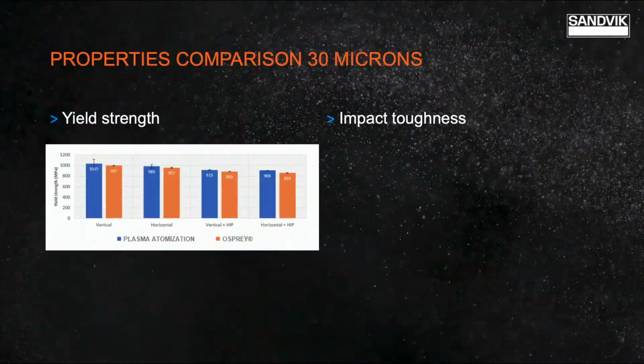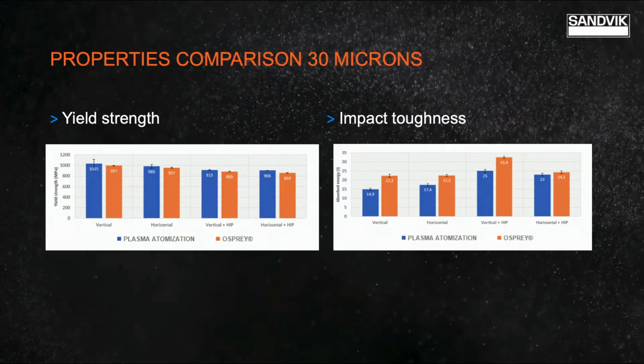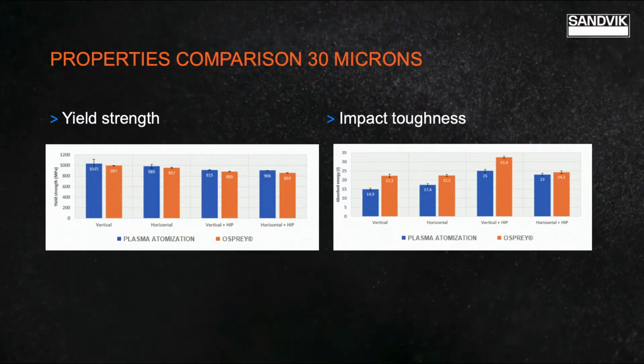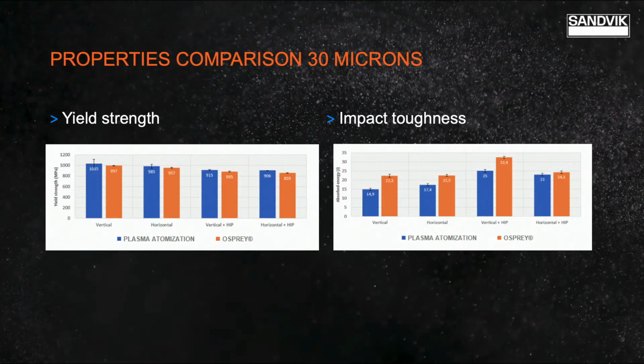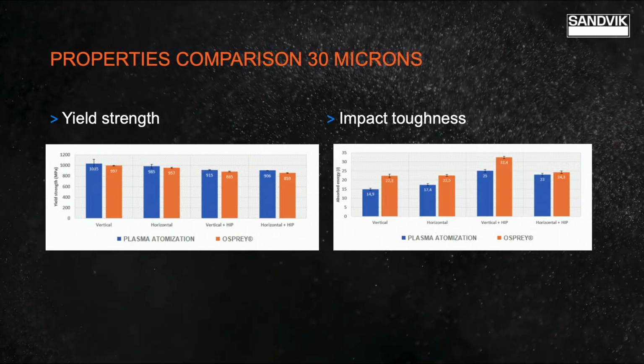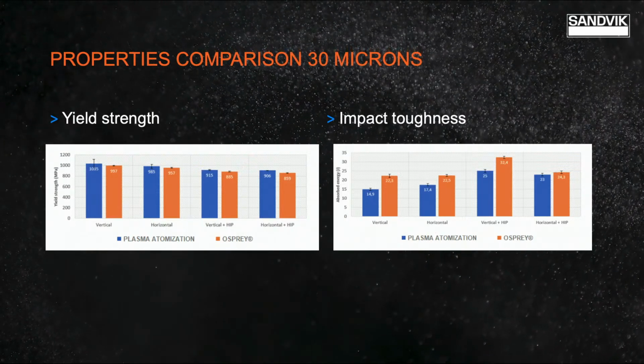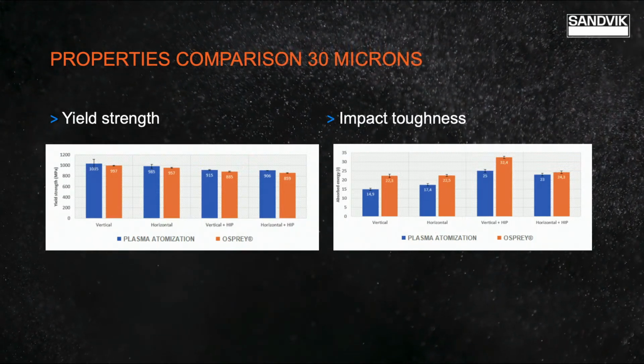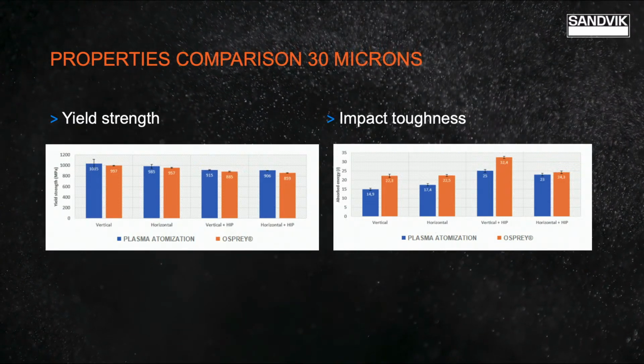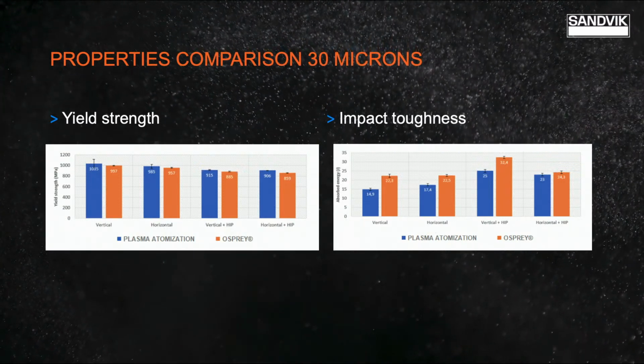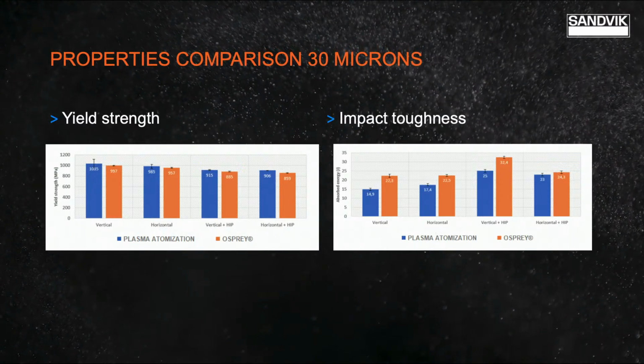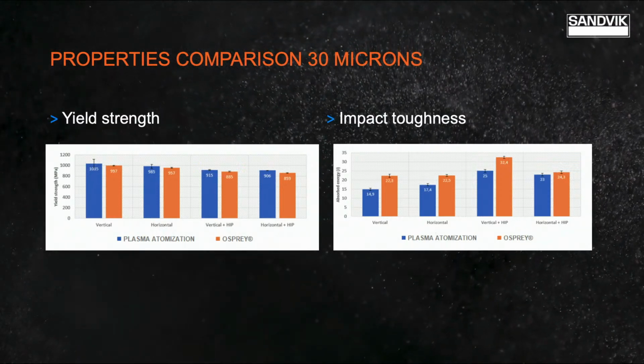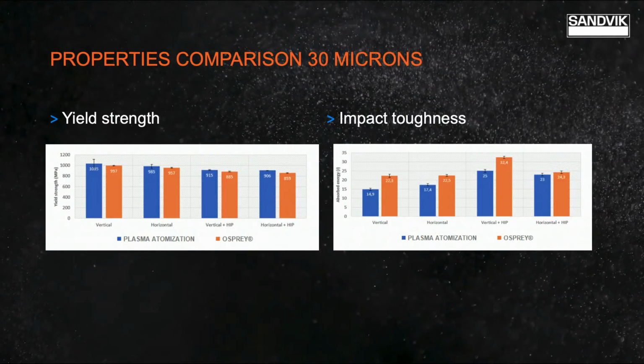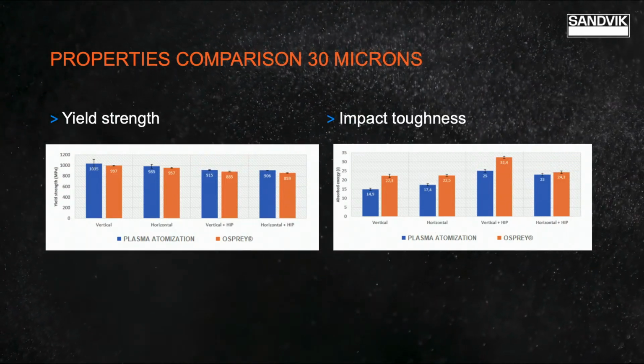What about the mechanical properties? Are they also good? Yeah, that's a fair question, Harold. And most of the viewers will want to know this. So when we print using a 30 micron layer thickness, we see very good mechanical properties. We can even achieve tensile and impact toughness properties that are at least comparable to the plasma atomized powders, as you can see on the screen. And especially when you take into account the error margin. So we achieve this by a very good control of the oxygen content and the process parameters, like you mentioned just now.